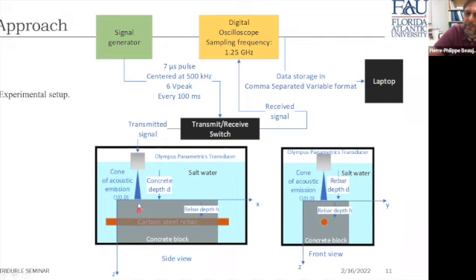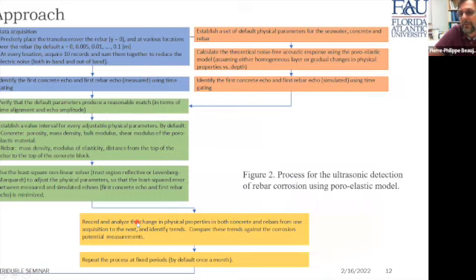The model we're using is focusing solely on what is happening in the concrete above the rebar and with the first echo of the carbon steel rebar. But the carbon steel rebar is relatively thin, and as a result, there could be an interference from the secondary echo coming from the bottom of the rebar, which currently we do not model.